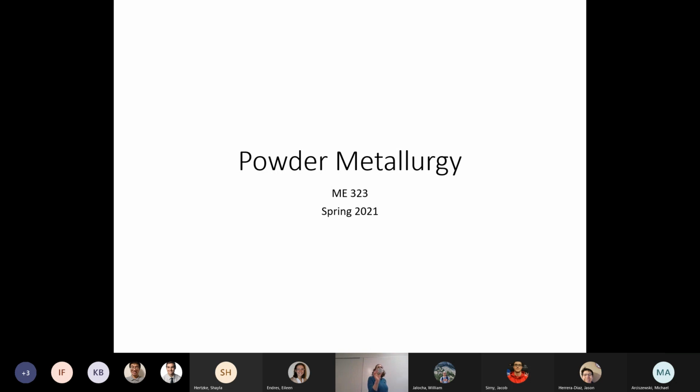So a reducing atmosphere is one that's a little more active. Oxygen is the problem. When you have metal in the presence of oxygen at high temperature, you can easily get oxide. Metal to metal will bond very well. Oxide to oxide does not bond as well.